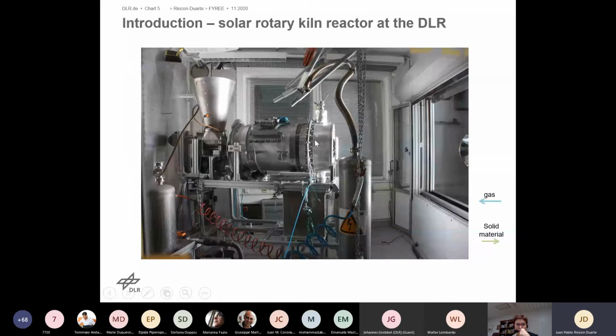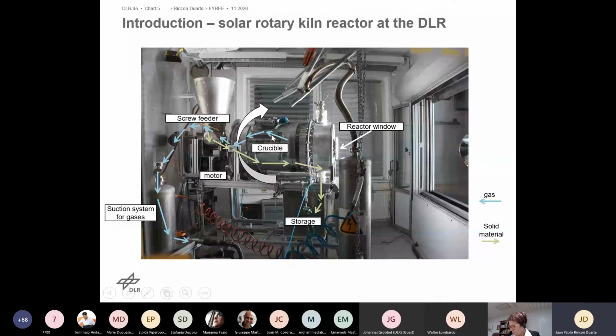So this is a picture of our solar rotary kiln taken during this campaign using the iron manganese oxide and in the solar simulator in Cologne. Here basically we have the material inside this hopper, and it is brought inside the reactor using a screw feeding system. Then because of the rotational movement of the crucible, and also because of the inclination of the kiln, the material will continue moving to the front, and then the material will leave the crucible and end up here in the storage. This part of the reactor can rotate while the front part is fixed. And here we have the aperture region where the solar radiation enters. Also, the gases taking part in the reaction or evolving from the reaction can be taken out from the backside of the reactor.